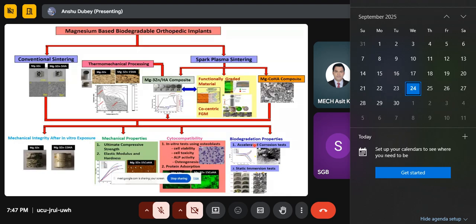Similarly, since degradation is a major property of magnesium, you need to check the degradation properties as well, because we need to see whether it is degrading too fast or whether it is degrading along with the healing of bone or not. Further, it should be mechanically stable. Otherwise, there is no point in developing such a material. And further, we even checked, after 3 days or 7 days or 14 days, whether the implant is sustaining such mechanical properties or not. Because if it is degrading too fast, the mechanical properties will drastically drop down.